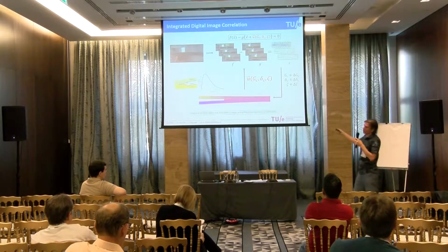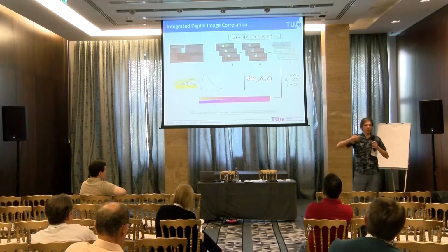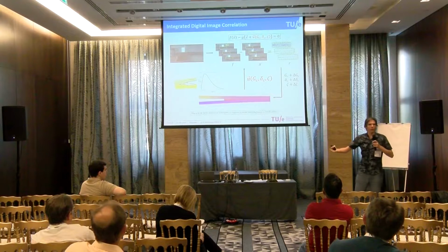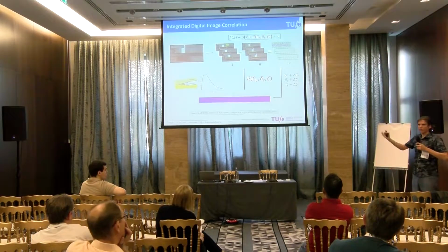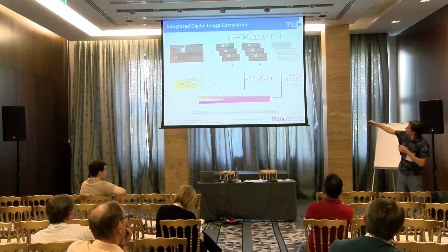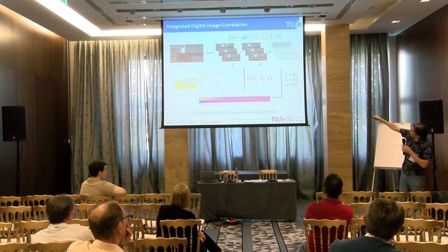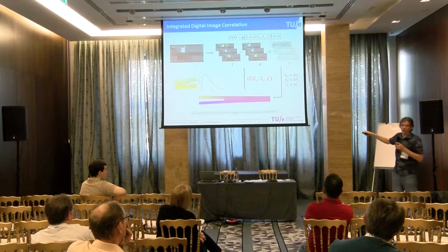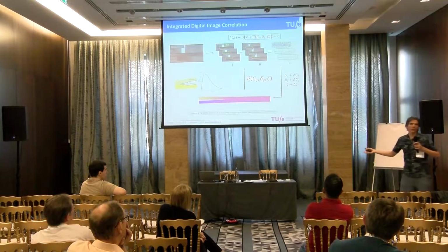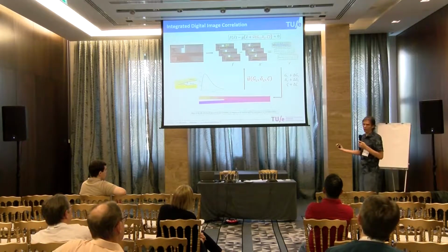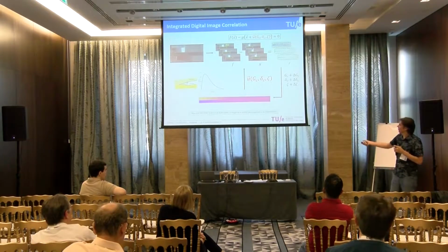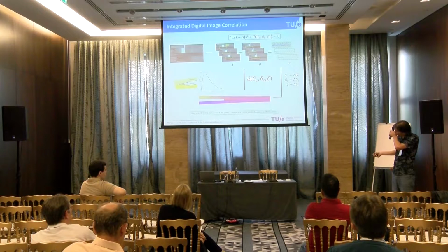It is a scheme where we do not first get displacements or strains and then use finite elements to correlate these; that would be finite element updating. In this way we directly warp our images back to our reference. We've shown in the past that this is a more robust scheme, and it is more sensitive to very small changes.